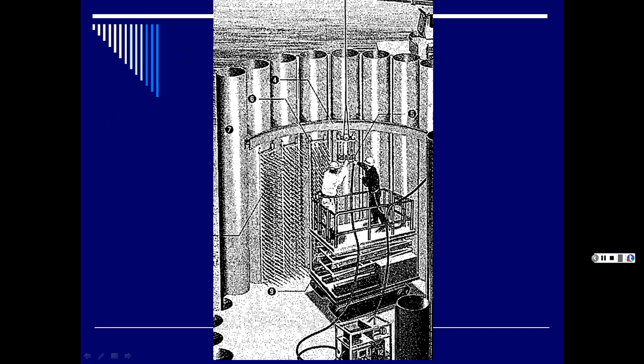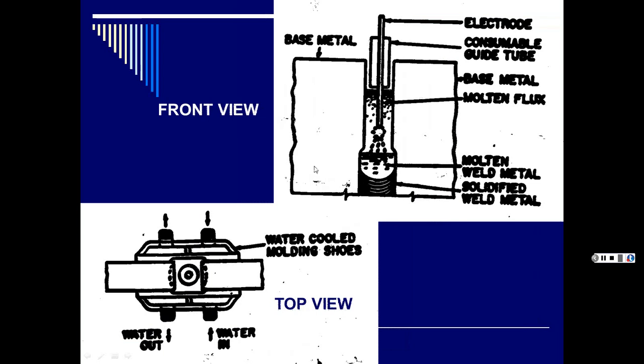Yeah, they're making something that they're going to use out in the ocean, and then this will go down in there, the vessel. And so it's running up a little track, just like it goes vertically when horizontally the sub arc works, which is easier, obviously, to use than having to do with all this mess. But they were able to figure out a way of making sub arc work vertically, and that's what this is basically about. And it has all this stuff to hold in the flux that's dumping in there. And then it has shoes on either side that hold all that stuff, and has water coming in and water coming out to cool the weld and keep it a certain temperature so it doesn't get too hot or too cool.